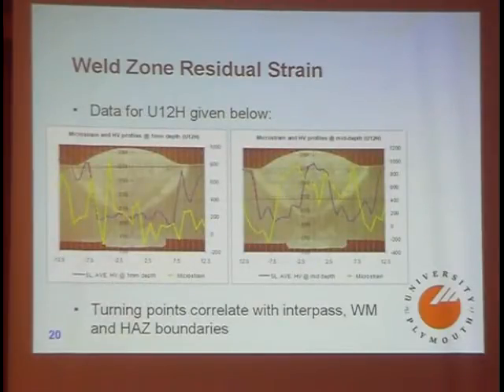So what you can then do is superimpose your residual strain profile along with the micro hardness profile on a macrograph of the weld and start trying to interpret what the data is doing. The yellow data here is microstrain. This blue purpley thing is micro hardness, and these are scaled correctly according to the macrograph of the weld, so that the toe reflects these gradients in that data. This is roughly for the 1 millimeter line, and that is for mid-depth. So you can then start going through this in some nauseous detail to try and identify trends and parameters that work. This is the work that was done by Matteo Bozzi in a rather good undergraduate project that he did at the University of Plymouth.